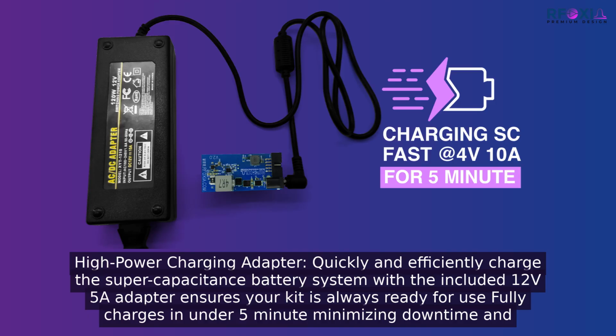This is the charging adapter, 12 volts at 5 amps, delivering 60 watts into the supercapacitor bank at 4 volts and 10 amps after conversion. At that input rate, the double layer forms across the activated carbon surface in under 5 minutes. A comparable lithium cell receiving this power level would plate metallic lithium and fail. The supercapacitor accepts it without complaint because it is not doing chemistry, it is doing surface physics.